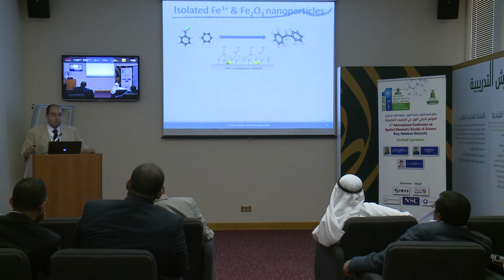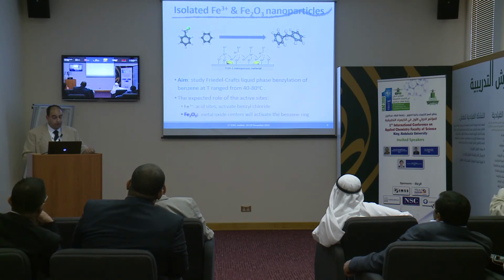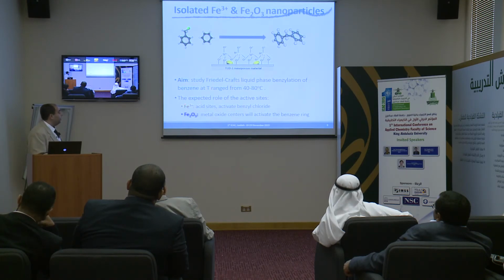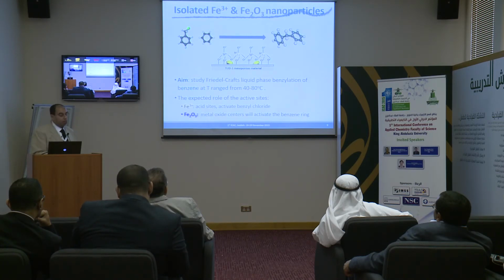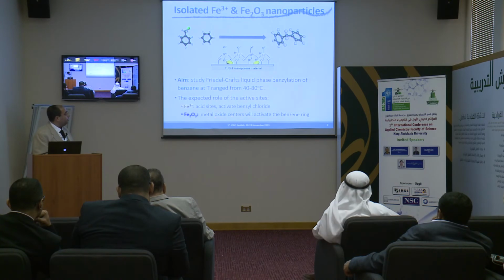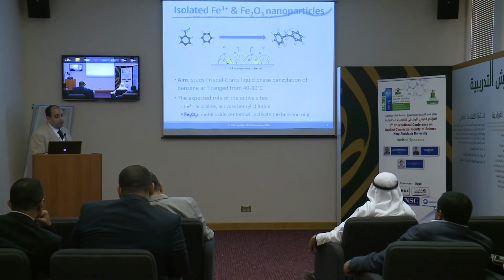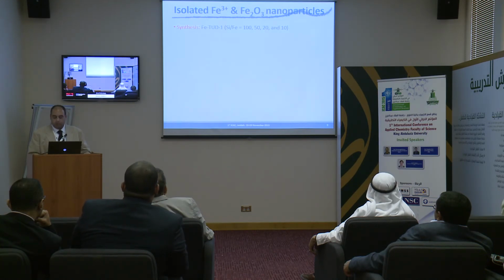We aim to use this system in the benzylation of benzene, a Friedel-Crafts type reaction, to form diphenylmethane at different temperatures. Our expectation before we started was that the acid sites in isolated iron 3 will activate benzyl chloride, one of the reactants, and in the presence of iron oxide nanoparticles, this metallic oxide center will activate the benzene ring. I will show you in a minute what the effect is of activating the two substrates instead of activating only one substrate. Well, this is the material that we prepared, iron TUD1 with different catalytic ratios.